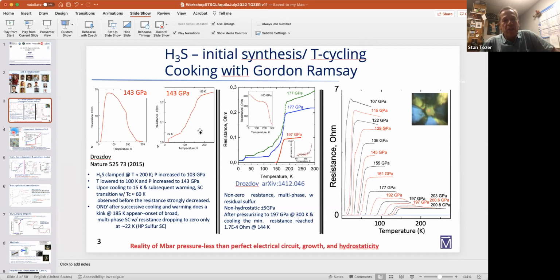But the initial synthesis was very complicated. Chemistry going on. Here you see that there's a transition. It looks somewhat like the sulfur transition, and only after working it back and forth a few times in temperature do they see indeed the sulfur transition at high pressures, and then this transition at 185, and then with additional annealing and increases of pressure, they were able to get the resistance to drop to 0. And then you can see in this final trace here, just this beautiful family of curves that they were able to obtain. But at the same time, they started over here, right?